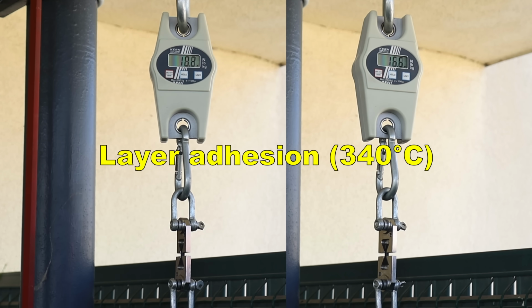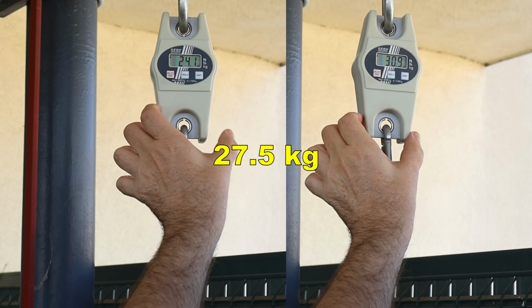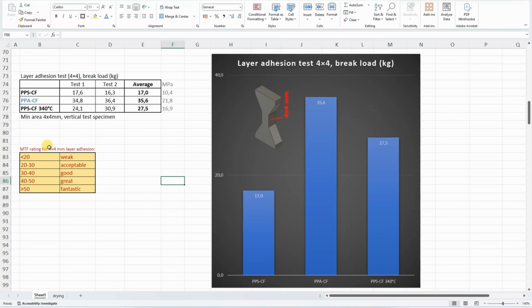Layer adhesion printed at 340 degrees Celsius. Noticeably stronger. Here you can see my rating for the layer adhesion for this test object, and we can see PPS-CF printed on default settings is quite weak.